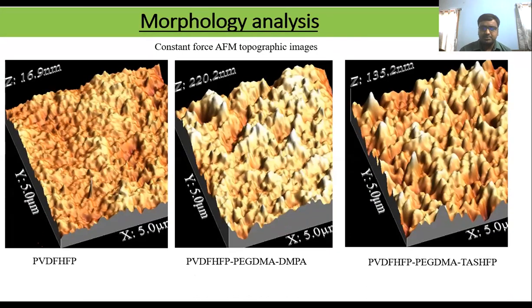So we also did some characterization, as I said. We used atomic force microscopy to do the surface characterization to understand what happened within the membrane while doing the cross-linking. So you can see this is just a control membrane using only the base polymer. If you introduce the cross-linking agent, the DMPA or PEGDMA, you can see the roughness within the membrane increases. This is indicated by the scale. Here the surface is very smooth, and from lower to top the height difference is 16 or 17 nanometers, but here it is like 220 or here about 140 nanometers. So this is how you can see the introduction of cross-linking agent in the membrane gives a higher surface area, which may be one of the reasons for the faster extraction or transport within the membrane.